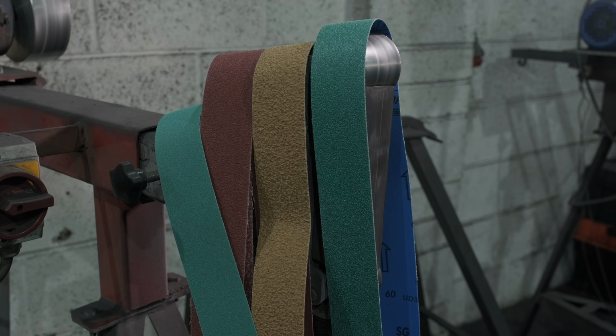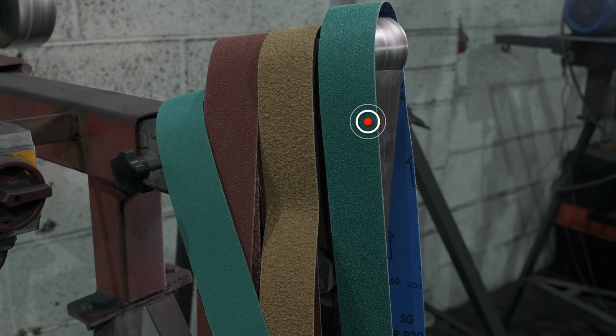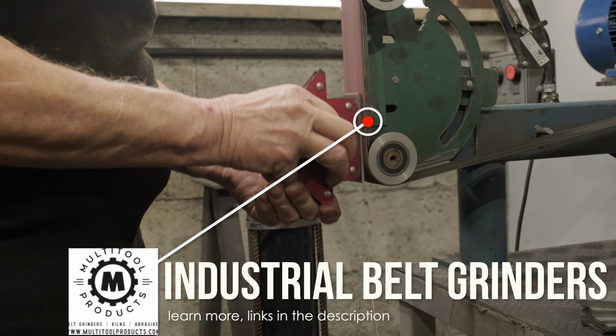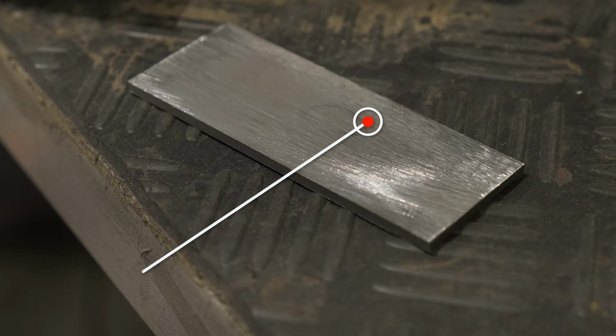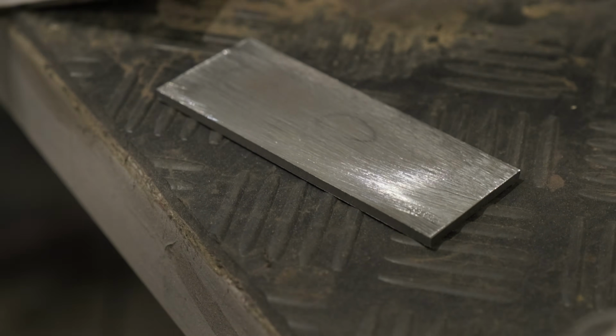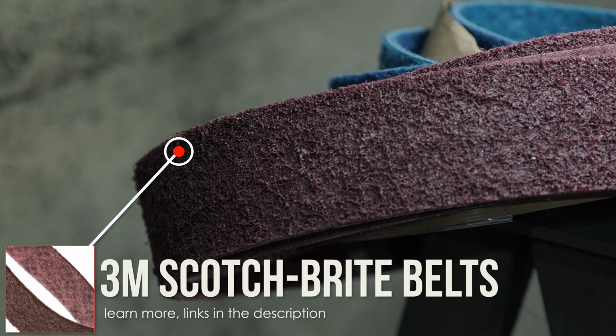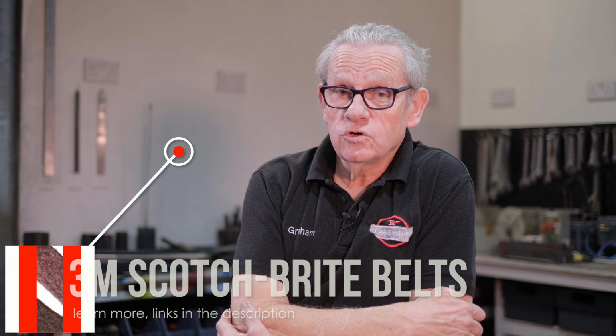So bringing that process back into what we're doing to make Damascus, I will degrease and then I will lightly abrade the surface. You can do it with a grinding belt. You can use a fairly coarse one. You can use a 36 or a 60 or an 80 grit belt, whichever suits your fancy. But to be quite honest, I use a 3M Scotch-Brite belt. Scotch-Brite belts come in various grades. The very coarse one, the coarsest of the lot, is absolutely magic, and it just scratches that surface with a very coarse satin finish on, and I never have any trouble welding stuff together.